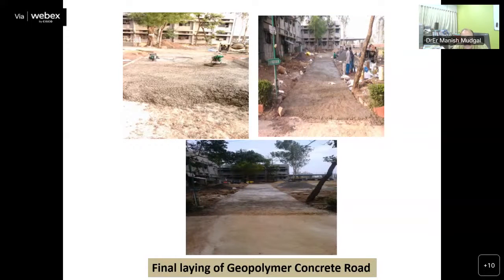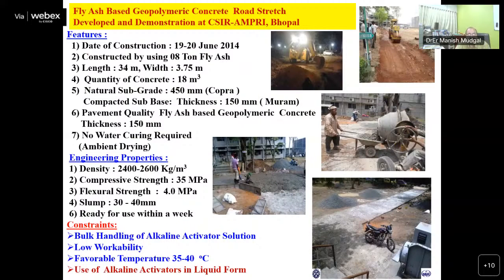This is the road patch we demonstrated in 2014, and the engineering properties are like this. Its strength was 35 MPa, flexural strength 4 MPa. At that time, the slump of this concrete was very low, because we made it with liquid alkaline activators. This is a limitation of this process: its workability is very low, it requires 35 to 40 degrees centigrade temperature, and bulk handling of alkaline activator solution is needed. These are the constraints of this process.